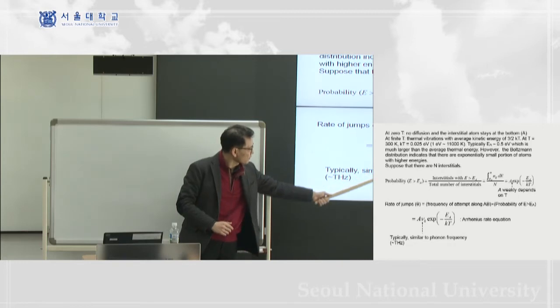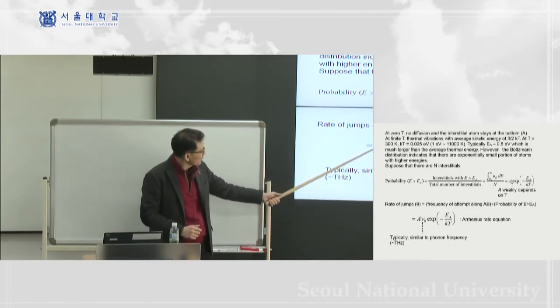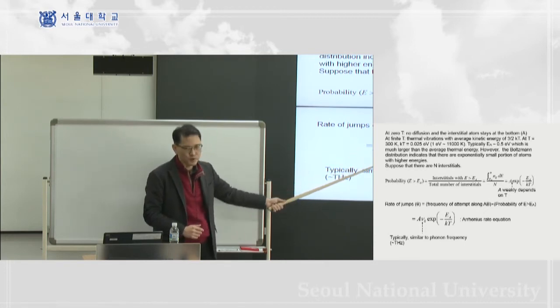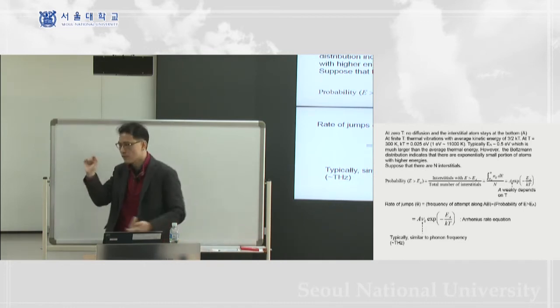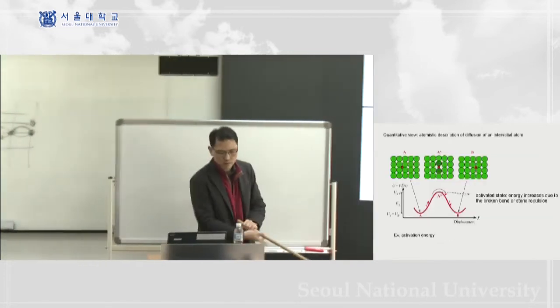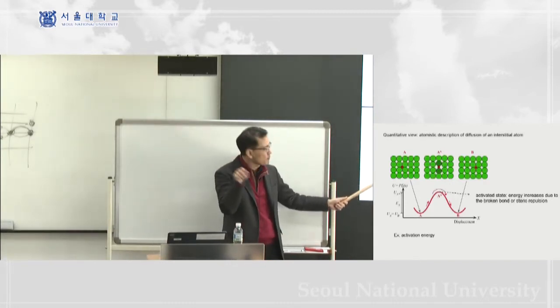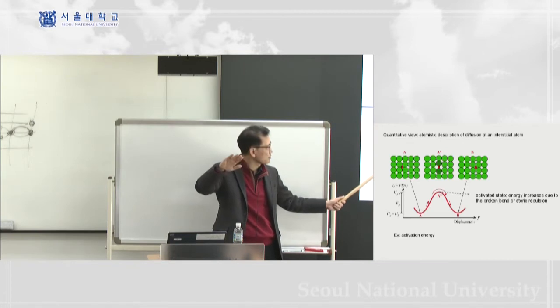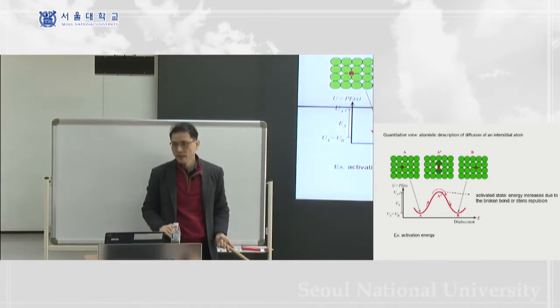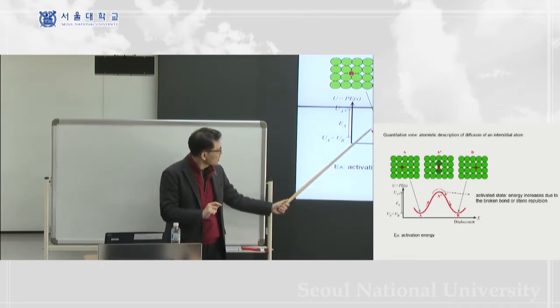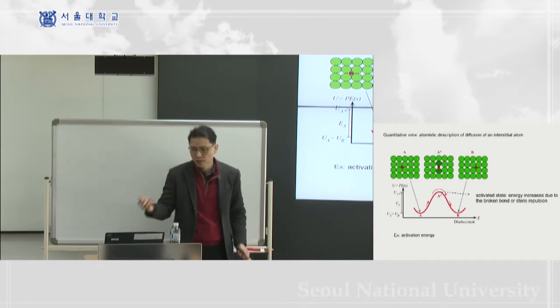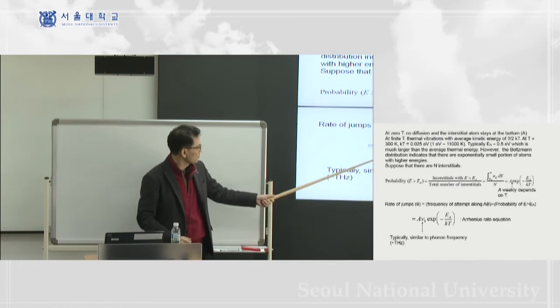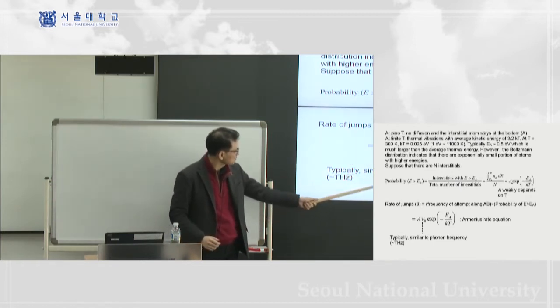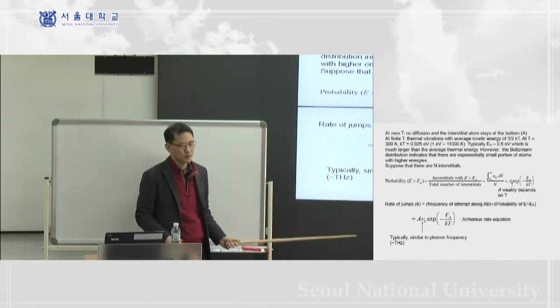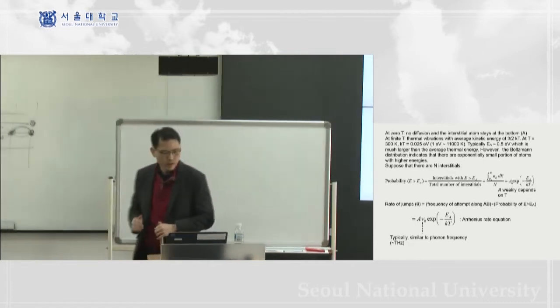All right, so this is the Boltzmann factor, times another important thing, the so-called attempt frequency. If you look at these atoms, they vibrate at finite temperature, and at a certain time they happen to have enough energy to go over the energy barrier, right? So the vibrational frequency also scales with the rate of the jump, and this is typically similar to the phonon frequency, which is about terahertz, so 10 to the 12 times per second.